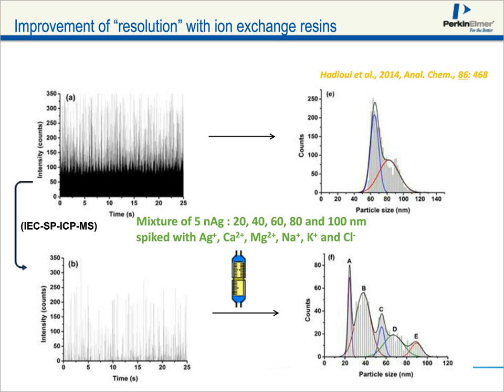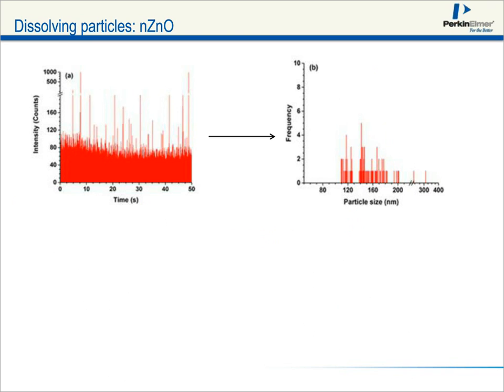So we're really getting some additional information by coupling with these different columns. And a last example for that, this is a nanoparticle that we're generally not able to see by single particle ICP-MS. Again, the problem being that the dissolved metal is just too high, so our noise is very high compared to our signal. And you see the result of that. This is a 50 nanometer nano zinc oxide, and you've got a few signals, but really just for probably the large agglomerates or large particles in that distribution.